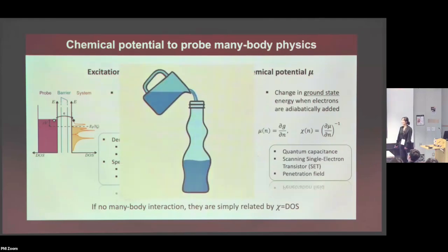One very pictorial analogy that I like to make is that you can imagine a water bottle, which can change its shape as you pour or remove water from it, okay? That water bottle shape is the many-body density of states. The excitation type of measurement would be measuring, for a particular water level, the entire shape of the bottle. You can also, of course, do it as a function of gating, but one measurement itself would be measuring the shape of the bottle. Whereas the chemical potential or thermodynamic measurement would be measuring this water level itself as you add the water, okay? So you're tracking how this water level changes as you add or remove more water. And of course, if you don't have any many-body interactions, the two would basically be measuring the same thing, because your water bottle is just rigid and not changing in shape. So that's the context.